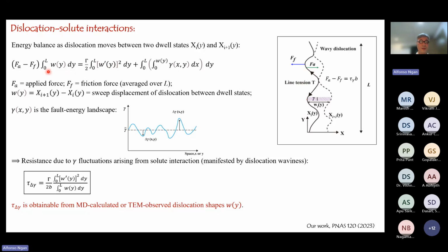And then from this, you basically can divide this equation by this integral, and then this term will be related to how much stress you need to apply to move the dislocation. It turns out that as long as I'm considering a long enough dislocation, this second term will vanish. So eventually you will conclude with this very simple formula. Here, this is the stress due to the fluctuation of the stacking fault energy, and it can be computed by this quantity on the right-hand side. Basically, if you know the shape change of the dislocation, and you can work out the derivative of it, and then do this integral on the top, and then this integral on the bottom, you can calculate this stress or resistance due to the fluctuating gamma.